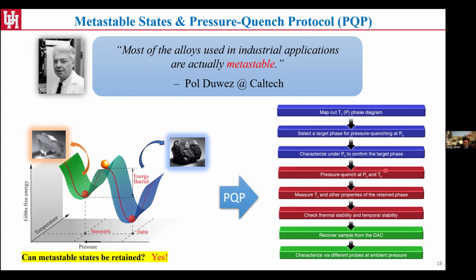Here I want to draw attention to the fact that temperature is very important. We did try to quench, quickly releasing the pressure at room temperature, and so far we haven't seen any success in all the materials we tried. So all this quenching happens at low temperature. Basically, we try 77 Kelvin and 4.2 Kelvin, the cryogenic temperatures for liquid nitrogen and liquid helium. After we quickly release the pressure at those quenching temperatures, we do a lot of measurements to confirm whether these high pressure properties are really locked in, or at least partially locked in. That's one reason. The other reason is that we need to check how stable they are: do they exist for only a few seconds, or can they survive for a few days or even a few months?